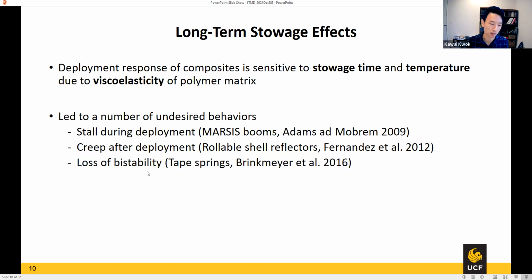And another thing that can happen is that you can actually change the structural behavior entirely, because one of the effects of viscoelasticity is to change the stability landscape of the structure. Tape springs can be made to have different stable configurations, and there was pioneering work on that from Sergio Pellegrino on how to make bistable tape springs, based on elastic tape springs. Later on, when we apply composites to make bistable tape springs, this problem came up: sometimes you actually lose the bistability if you stow it for too long.